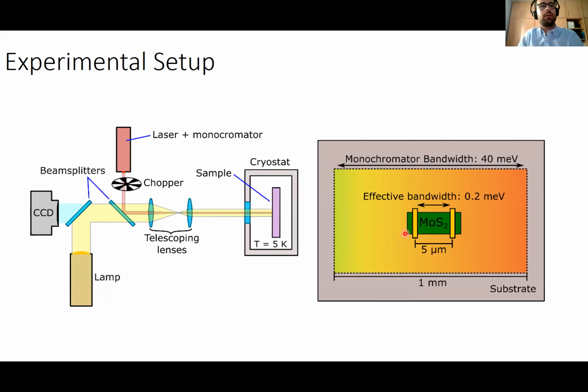So we have developed an experimental setup, of which we have a schematic here. Here we have the light source, which is a supercontinuum laser plus a monochromator that allows us to select the excitation wavelength of the light. Here we have an optical chopper that allows us to modulate the frequency of the excitation light. Here we have two telescoping lenses that allow us to collimate and focalize the light over the sample.